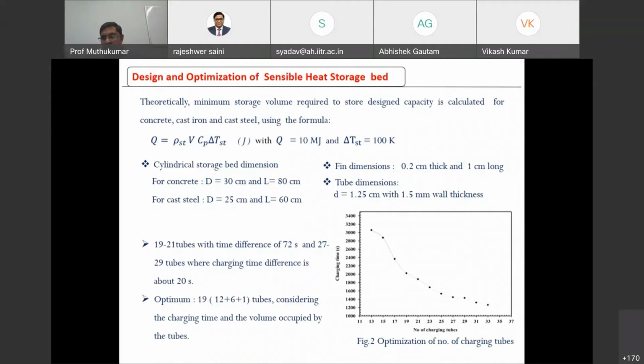If you choose the number of tubes between 27 to 29, the volume left for storing the heat storage material will be very low, because the tubes themselves will occupy more volume. Then obviously you cannot get the desired capacity of, say, 50 megajoule or 100 megajoule, whatever it may be. So the higher number of tubes is ruled out. If you choose between 19 to 21, though we are sacrificing a little bit of charging time, the available volume for storing the material will be good enough. So you can choose 19 charging tubes: one tube at the center, 6 tubes in the first row, and then 12 tubes in the next circle. In that way you can optimize.